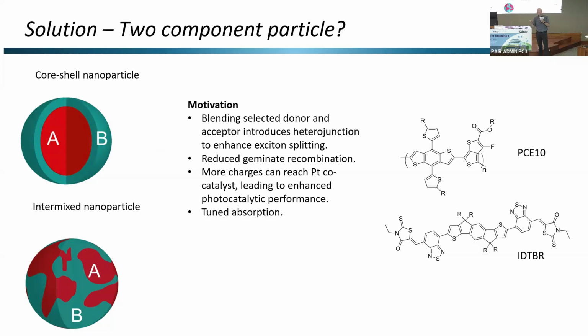But when we started to think about this, we thought maybe there are two types of two-material particles that could occur. One would be this so-called core-shell type nanoparticle, where you've got a donor and acceptor, and it can either be in the core or in the shell. And we thought this would probably be the most common, because typically two components have different surface tensions, different surface energies. So one would be preferentially radially driven to the surface, as in a nano emulsion technique. And as the nanoparticle dries from solvent, one of the components would preferentially go to the surface, just typical thermodynamics.